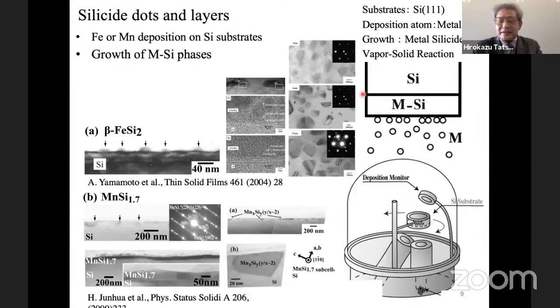So on the substrate, kept at higher temperatures, metal atoms are deposited, and the atoms react with atoms from the substrate by interdiffusion. The simple growth system is like this. Iron is deposited at low deposition densities, and nano-sized nanorods are formed on the substrate. The structural property was characterized like this.